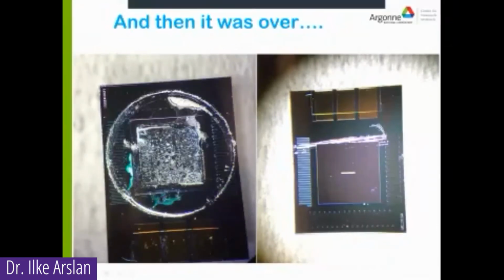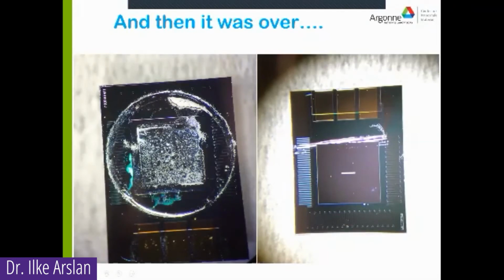because there was a polymer coating on this chip. And this synthesis occurs with pH between 12 and 14, and at elevated temperatures at 70 degrees. So it just ate right through that polymer coating and then hit the contacts, and then it short circuited. I mean, nothing happened to the microscope, but the experiment stopped. It wasn't heating anymore. So like I said, this is something that we're continuing to work with, looking for different chips, looking for different coatings, looking for different materials so that we can understand this important synthesis.